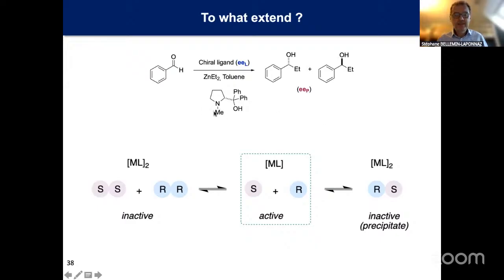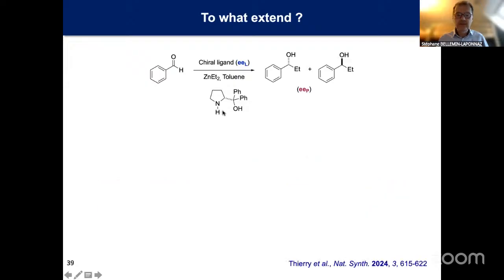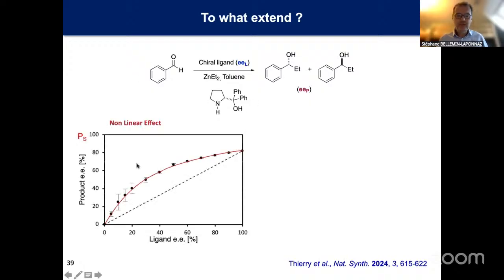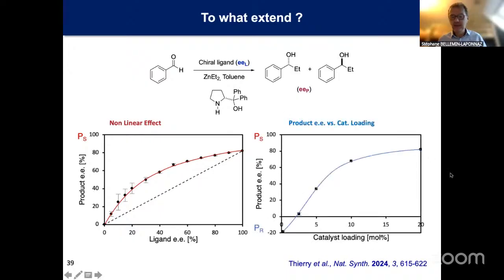So here, using this N-methyl diphenyl prolinol, you have the basic mechanism that can explain nonlinear effect. That is the fact that you have mononuclear species that tend to make dimers, and the heterochiral dimer is precipitating, and you have positive nonlinear effect. So now let's make a little change there and remove this methyl. Let's have a look at the reaction when you have only a hydrogen instead of a methyl, which is a very little change. And we know that the mononuclear species is exactly the same. If you look at this reaction with this very simple change, what you have is again a positive effect. But now if you look at the impact of the catalyst loading, you have a very strange behavior. Depending on the catalyst loading, you can generate one enantiomer or the other enantiomer. And you can see that this is a very strong change between low and high catalyst loading.